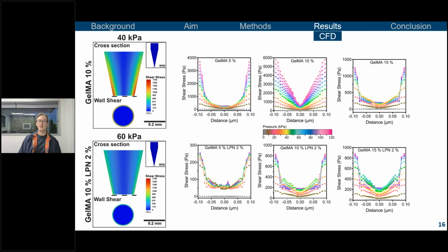We then performed some CFD, some computational fluid dynamics, on a three-dimensional model of our nozzle, the 27 gauge, just to get an understanding and a comparison between GelMA, which is our Newtonian-like material, and GelMA with laponite 2% at their corrected pressures that can be printed, and to get an idea of what their shear stresses were like. What we're able to see is that with the Newtonian-like behavior of GelMA 5 to 15%, there's an increase in shear stress compared to the addition of laponite, which significantly reduces your shear stress, particularly on the outer walls, which is very important for the printing of cells, as you want them to undergo limited shear stress.